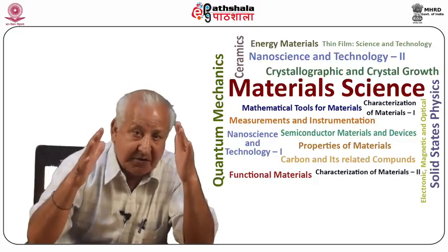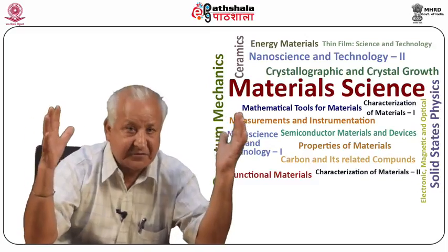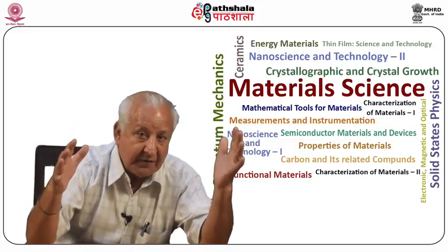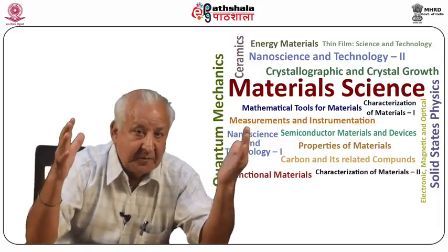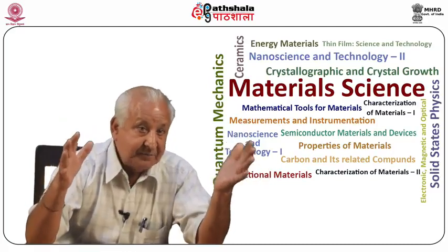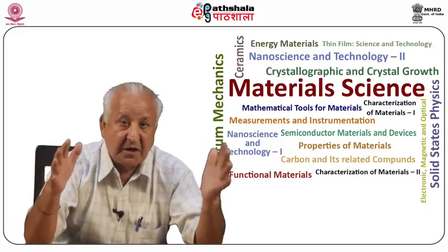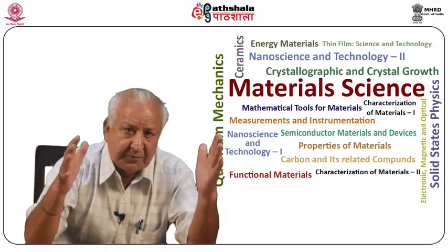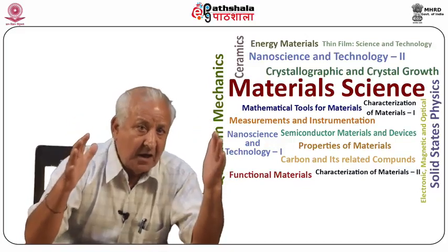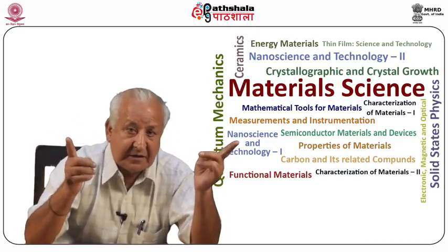That in the body-centered cubic structure, there are certain H', K', L' reflections which are present in case of a simple cubic structure bearing the same cube edge dimensions but get missing can be physically understood by referring to figure 14.2. As an example, for BCC structure, there is no 1, 0, 0 reflection, but 2, 0, 0 reflection does take place. Similarly, there is no 1, 1, 1 reflection, but 2, 2, 2 reflection is present. Let us take into consideration 1, 0, 0 reflection first. For simple cubic structure, the beams getting reflected from the top and bottom cube faces of the unit cell are out of phase by 2 pi for the 1, 0, 0 diffraction direction. This is not so in case of body-centered cubic structure.